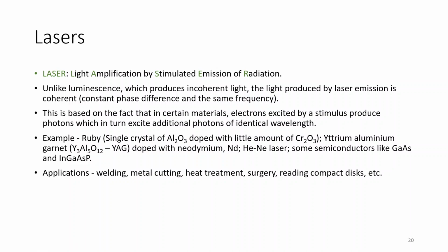Next application is lasers, which stands for light amplification by stimulated emission of radiation. Unlike luminescence, which produces incoherent light, the light produced by laser emission is coherent, with constant phase difference and the same frequency. This is based on the fact that in certain materials, electrons excited by a stimulus produce photons, which in turn excite additional photons of identical wavelength.